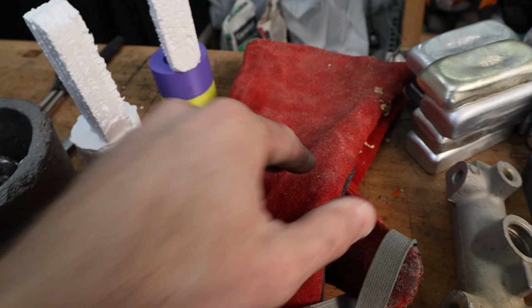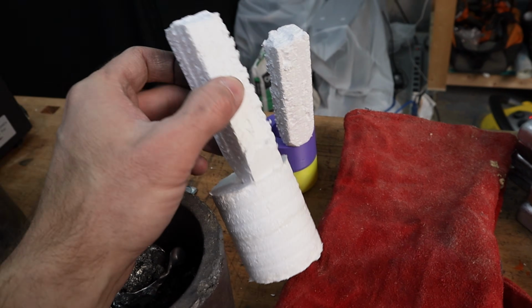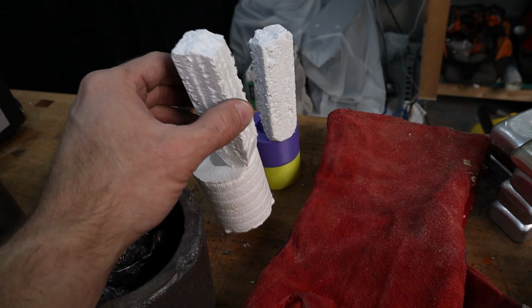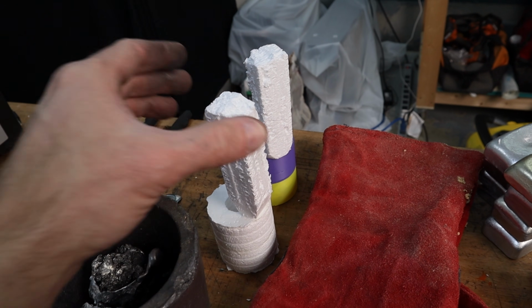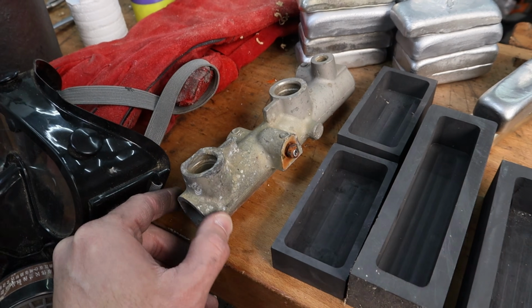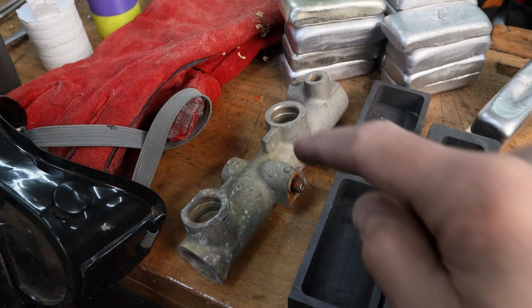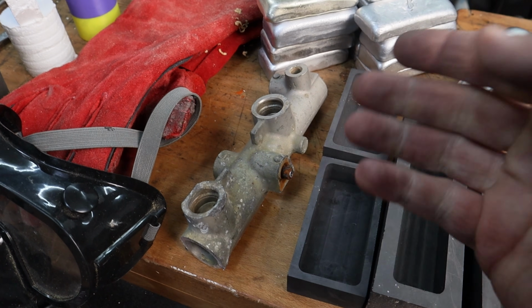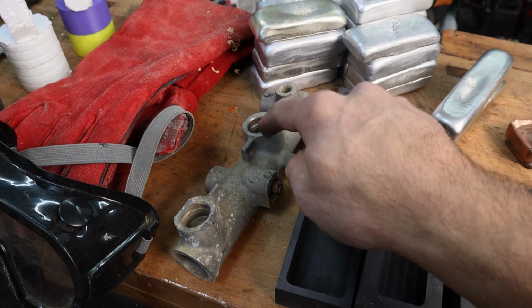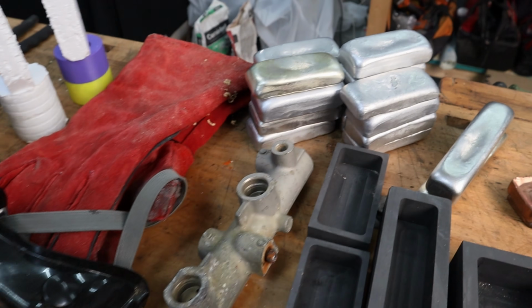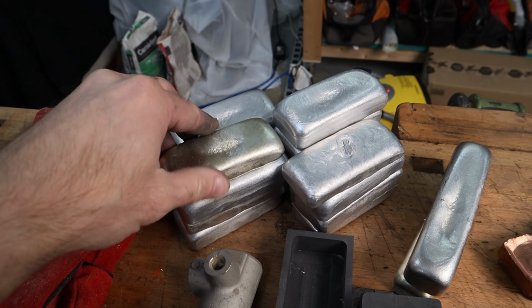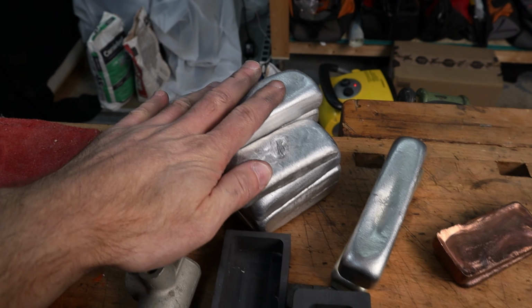I have some welding gloves. That's especially important because when we do this process, it's going to be burning out and creating a whole bunch of fumes as this burns out. We're going to need something to melt as well, and ideally it's going to be cast aluminum and not extruded aluminum. The chemical composition for cast aluminum is slightly different. And we're going to get something that looks kind of like this. These are all aluminum here.